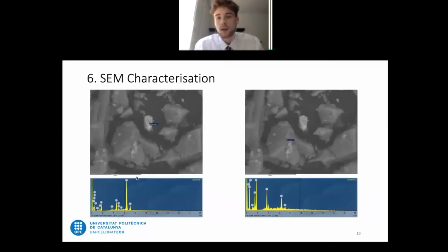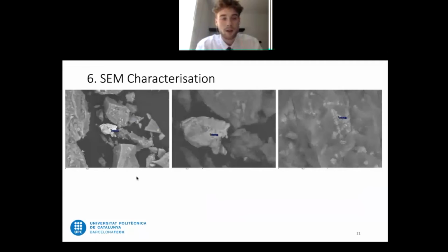So what we can get from this is that by viewing these images, we can see that the brighter areas within these backscattered images correspond to areas where reduction may have occurred, and the darker areas correspond to where reduction is most unlikely to have occurred. So moving on to the second area that was analyzed, as we can see, there's a general increase in magnification on this one particle. This particle is fairly bright, and then it starts getting darker and darker. And by the image on the far right, we can see there's only tiny abundances of these brighter areas.